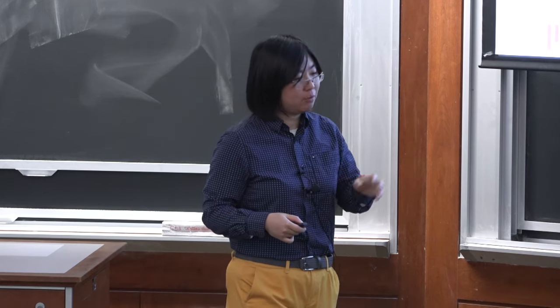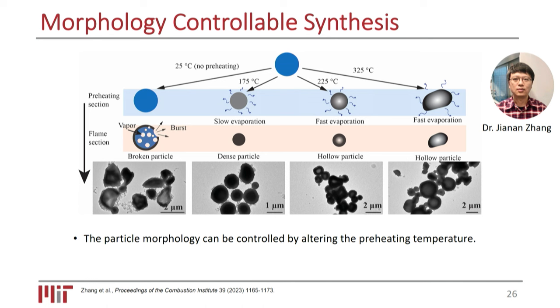And very briefly, I will also introduce our work on how we can control the morphology. I just mentioned how we can control the element distribution to achieve good performance. But performance not only depends on the composition, but also on the morphology. And that's another work that Jianan did in the past couple of years, where we can actually control the temperature history by carefully selecting the temperature profile inside the preheating chamber and the flame zone, such that we can control the morphology. We want to avoid scenarios like these, the broken particles, which do not have very good mechanical strength, and in terms of performance, they are not going to be good.